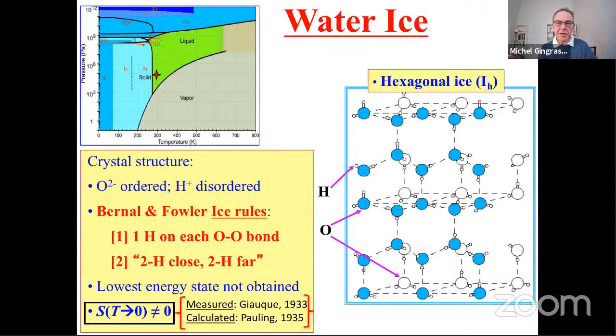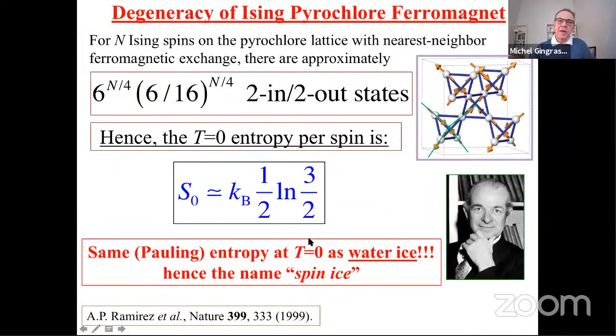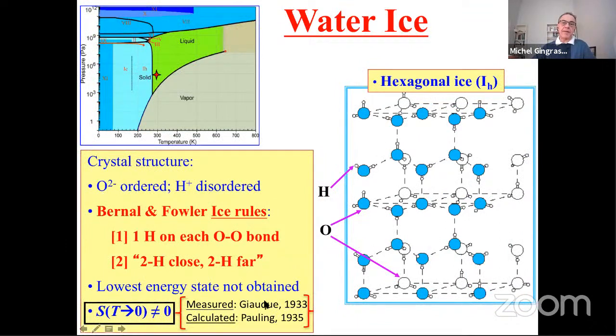And this is in disaccord with the third law of thermodynamics, that a system should have zero entropy at zero temperature. So two years later, Linus Pauling took these Bernal-Fowler ice rules, in particular the second one, and estimated how many hydrogen bonding configurations are compatible with this hydrogen bond structure of water ice, and estimated the number of ground states, and therefore the residual entropy, and he obtained this number here. And this number agrees within 10% with the residual entropy that Giauque measured for water ice. So water ice is actually a phenomenal system.